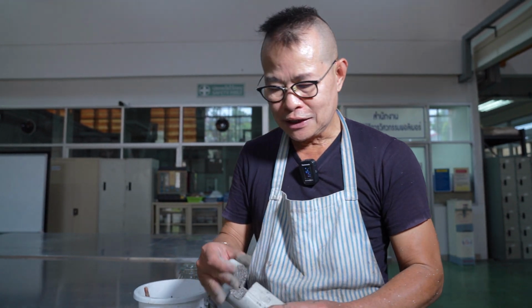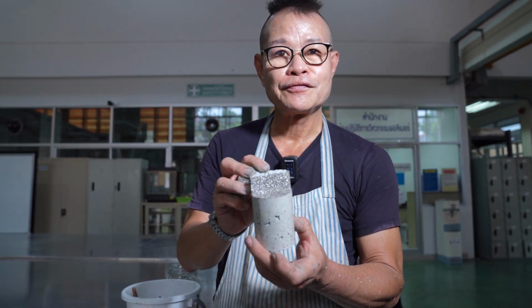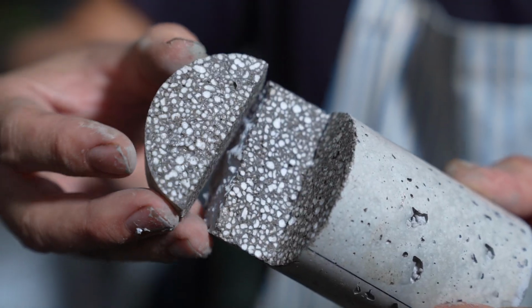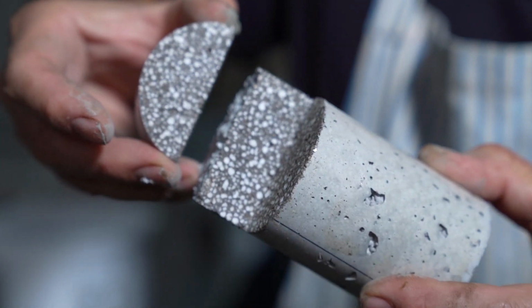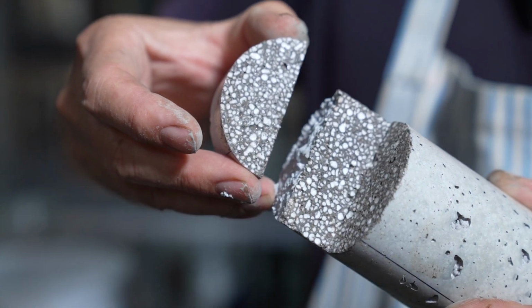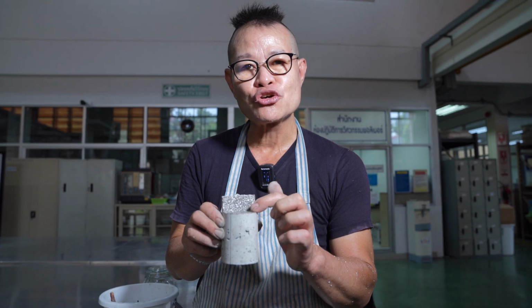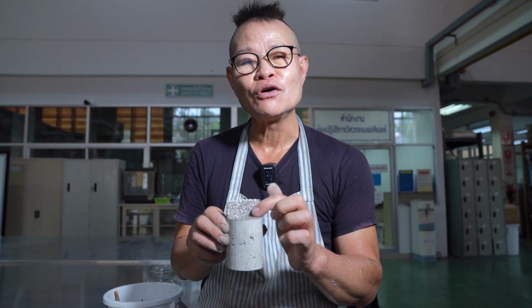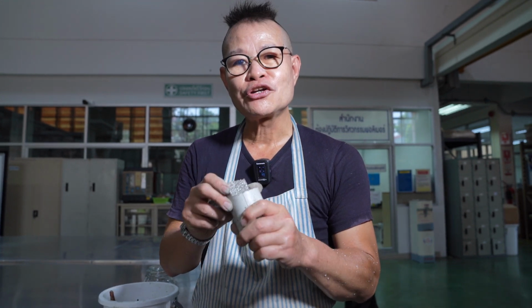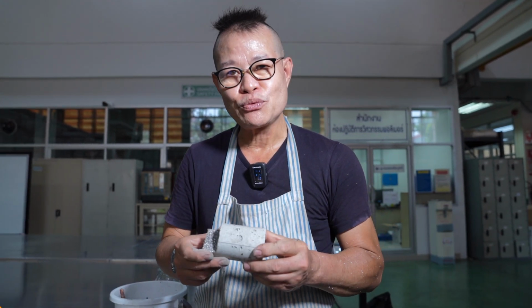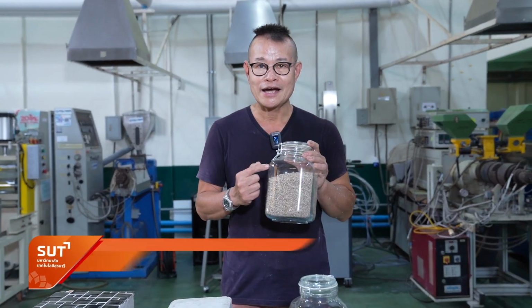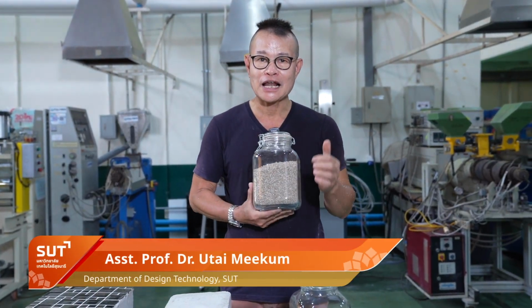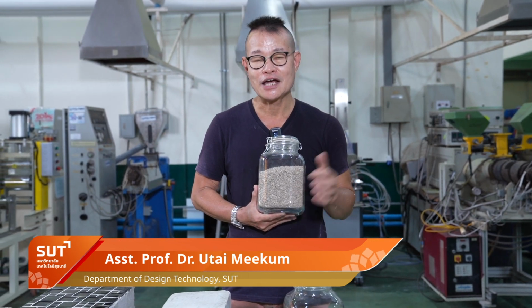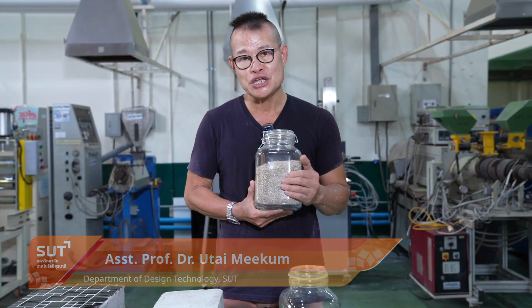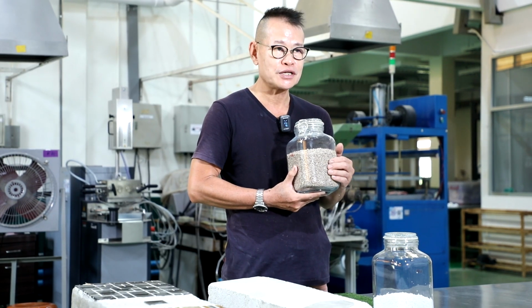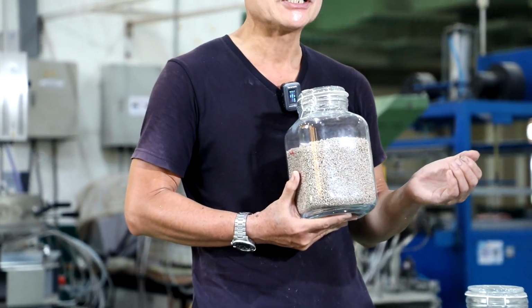If we have a look inside the block, we can see a very high compaction of lightweight engineered aggregate, polystyrene foams, and also the adhesion between the concrete and polystyrene foam is very, very strong, and makes that concrete block very strong and lightweight. So after one night of curing, you have the lightweight engineered aggregate, right? From this lightweight engineered aggregate, you can use it for a variety of applications, right?